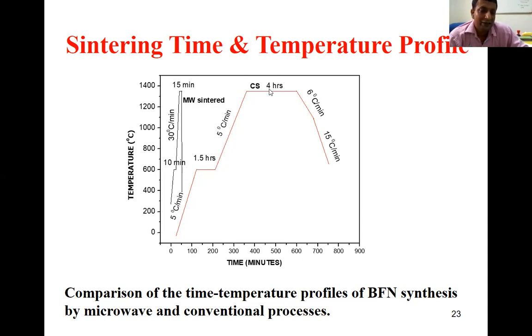But in the case of the microwave heating, you just see within less than 1 hour actually this whole sintering process is completed. On one hand, there's 14 hours, on the other hand there's 1 hour. So that's what was there actually. So a lot of energy is saved via this microwave heating process. And here